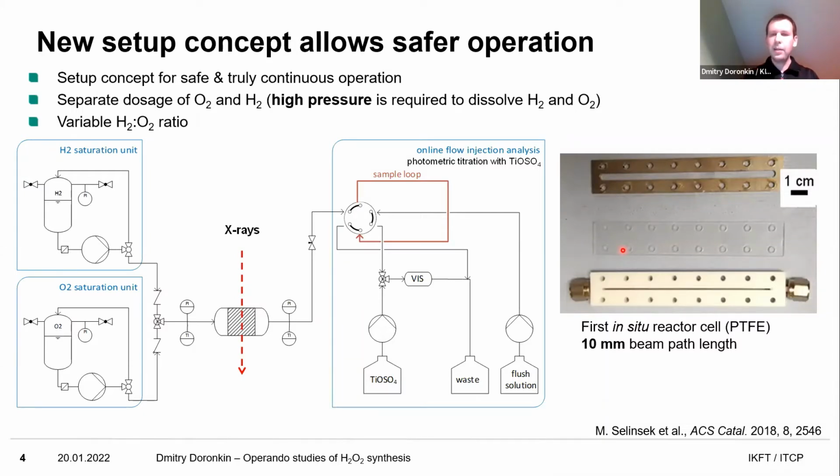Of course, if we require some expensive machinery, that's maybe difficult for everybody. But if we're dealing with Teflon PTFE, a brick of PTFE costs you $5 on eBay, and you can machine it in your garage. So it's quite simple. And compared to quartz capillaries, you can tune it directly to the size or volume, or I'm talking about beam path length, so that you get good spectra, not simply what you have off the shelf, but spend a couple of hours in your garage and size it to your needs.